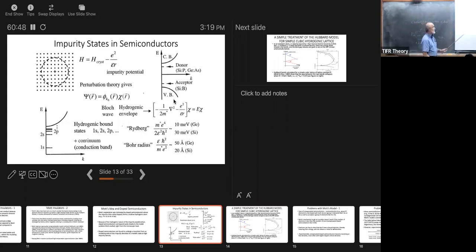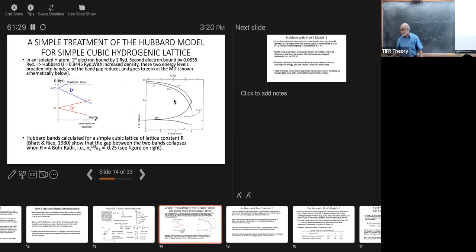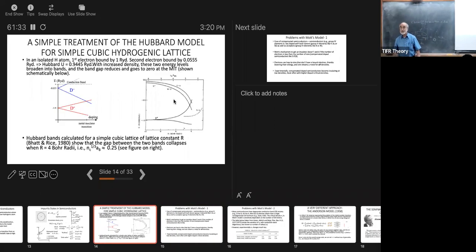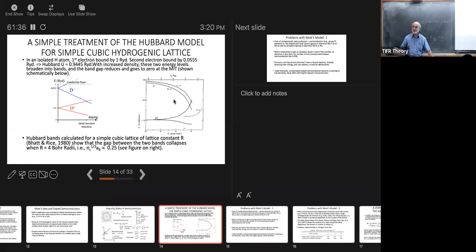So the main message is it's much, much bigger than the nearest neighbor distance in silicon or germanium or gallium arsenide. So on this scale, the lattice is just like a continuum, because you're talking about a wave function that's fat and big, and the lattice structure is on a very tiny scale. So we don't really need to worry about that, other than the fact that there is the Bloch wave that's coming here. But the physics of this system is very similar to that of hydrogen atoms in free space. The fact that its scales are very different is mainly due to epsilon being large. Basically, m star over epsilon squared is 1 over 50 roughly.